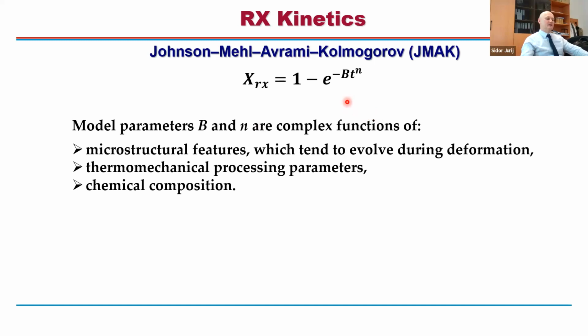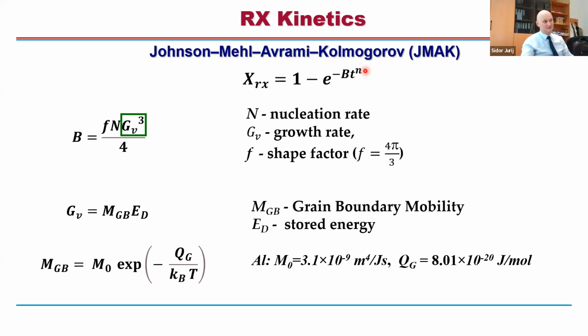So there are a couple of model parameters like the B parameter and the N parameter. We can say that they are material related parameters. Yes, that's true. However, you want to understand how to calculate or how to estimate these B and N parameters. So the fraction of recrystallized grains basically depends on two model parameters B and N, and here you have time. Right, so these model parameters B and N are complex functions of microstructural features which tend to evolve during deformation, thermomechanical process parameters and chemical composition, which means that for different chemical compositions, you will have different B and N values.